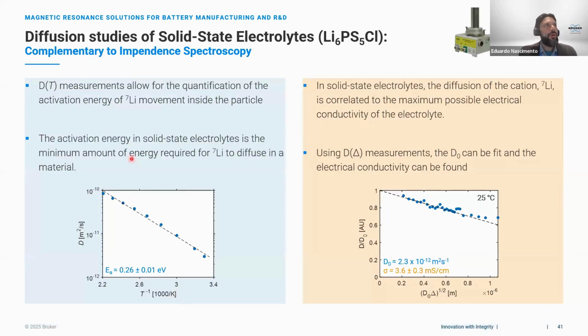Here is just an example of diffusion studies where, when you vary the temperature of the sample and calculate the diffusion, you can actually calculate the activation energy, which is the minimum energy required to move the ion in the battery. You can do that using NMR, and this can also influence the ion mobility. With diffusion experiments where you change the diffusion time, you can calculate the electrical conductivity, which are both important pieces of information when we are talking about developing fast charging batteries.